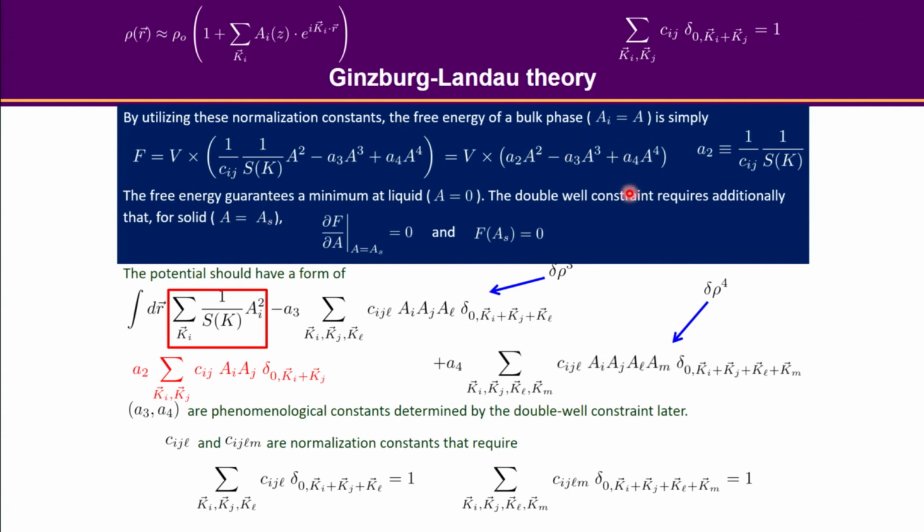Quickly you can get A3 and A4, which are associated back to the structure factor and the solid amplitude. So you will also need to get this input from your MD simulation. Where you have a solid, from there you can take a time average of the density profile and do a Fourier transform, which will give you the solid amplitude AS.